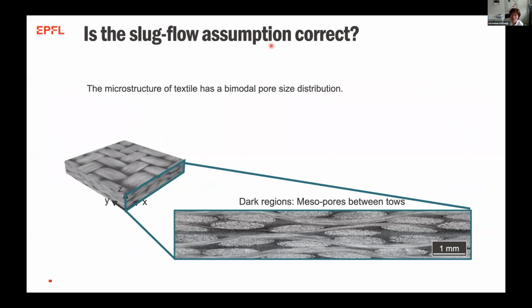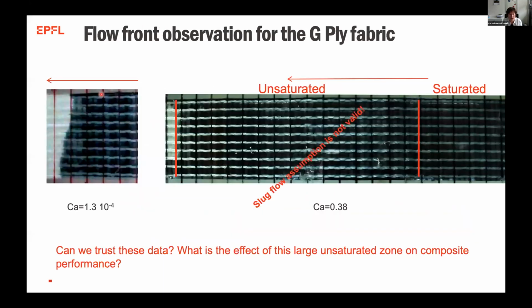So is the slug flow assumption correct? Well, the slug flow assumption, as I mentioned, says that basically the flow front progresses in a very, very flat manner. Here I have purely dry fabric, and here I have purely saturated fabric. So the saturation should go from 0 to 1 drastically. Here, of course, by looking at it, saturation is 0 here, it's 1 here, and in between I have a very slow progressive saturation.